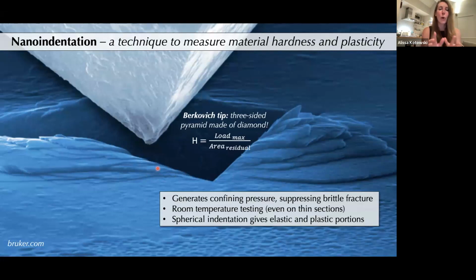And the Berkovich tip, though, is a problem for us because the tip is so sharp that basically the sample will yield plastically immediately upon pressing into it. But we are actually interested both in elastic and plastic deformation. So in order to circumvent this, what we do is use a rounded spherical tip instead. This allows us to deform the material elastically first, and then actually measure the plastic response as well. So we can convert the data then to be able to look at things like stress strain curves and be able to use that to calculate yield hardness, for example, but also to look at post-yield behavior.